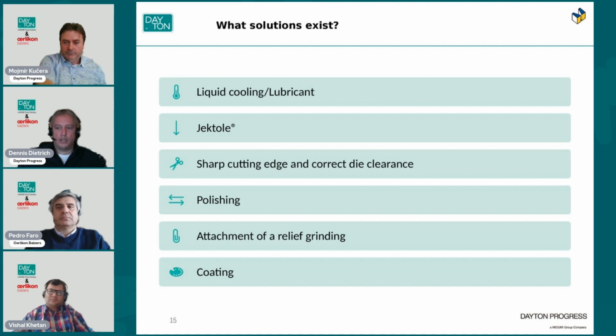The spring-loaded Jektole pin is a method to retain the slug in the die button after perforating. The Jektole punch also has a side vent hole which allows air to get in, breaking the vacuum. Also, a sharp cutting edge and the correct die clearance is required. When perforating the softer aluminium grades, significant hole shrinking may be experienced. Utilizing the proper die clearance, the amount of hole shrinking can be managed.